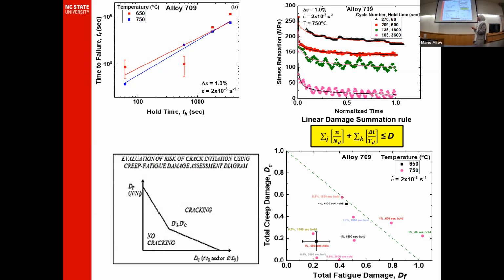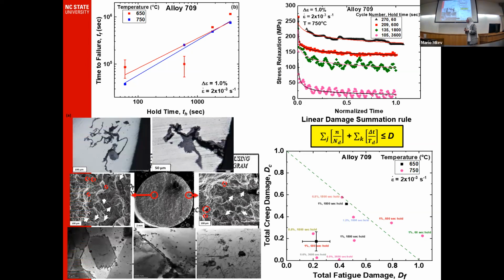One of the things we look at when we study mechanical properties of structural materials is the microstructure under microscopes. We use optical microscopy to look at the free surfaces of the sample, and we notice that when we increase the hold time or the creep damage, oxidation penetrates through these cracks. Since oxidation is a time-dependent process, increasing hold time means more oxidation penetrating these cracks, so we observe wider cracks with longer hold times.